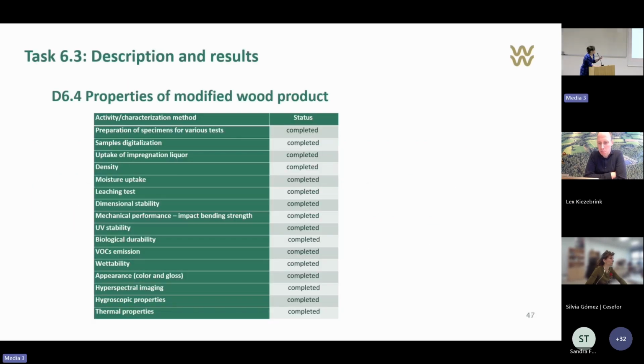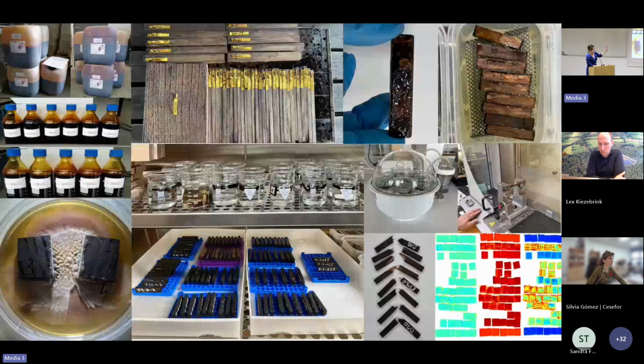Okay, so I will continue with the screening phase. Here you can see a lot of tests we were running on all of this radiata pine, which was treated with 10 different formulations, in the big screening phase. We received several hundred or maybe thousands of samples, and then we were dividing them to the tests. This is just a snapshot of the different tests we were doing, such as leaching, durability, and hyperspectral imaging regarding where the formulation is penetrating the wood.